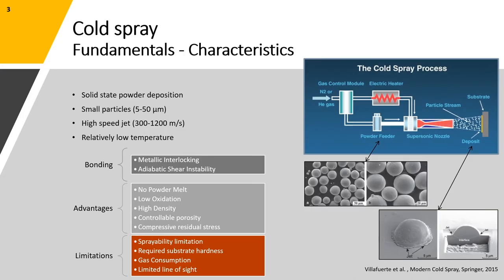Cold spray is a solid state powder deposition method in which small particles of micron scale are carried with a gas of relatively low temperature and while being conveyed through a de Laval nozzle, they achieve supersonic velocities somewhere between 300 to 1200 meters per second. After that, they hit the substrate surface. Upon impacting the substrate surface, they attach to it because of two basic phenomena, metallic interlocking and adiabatic shear instability.